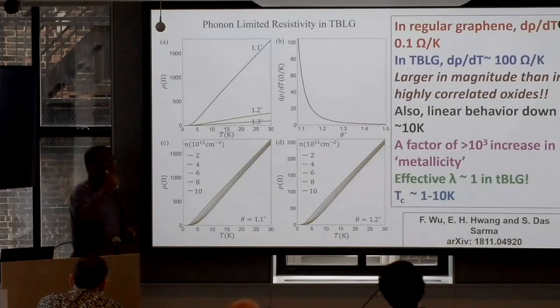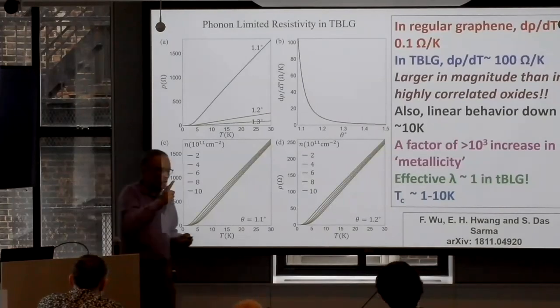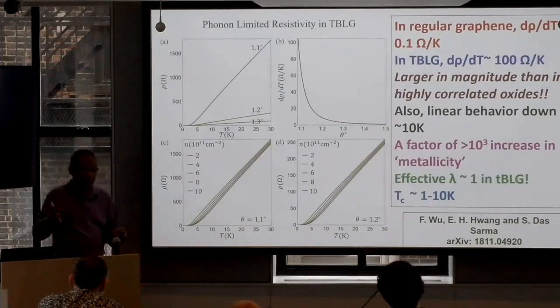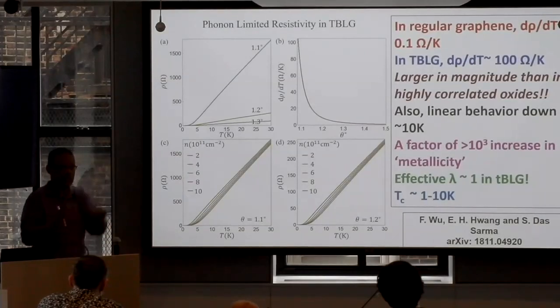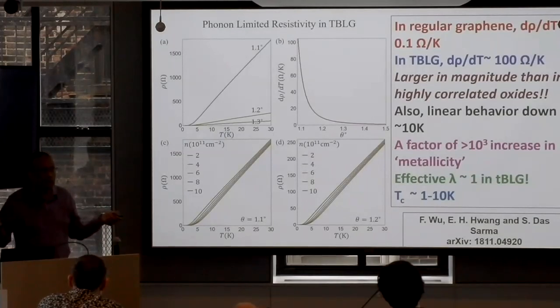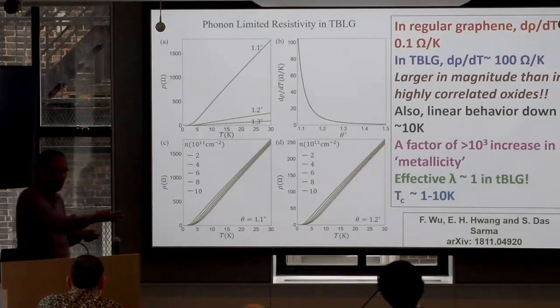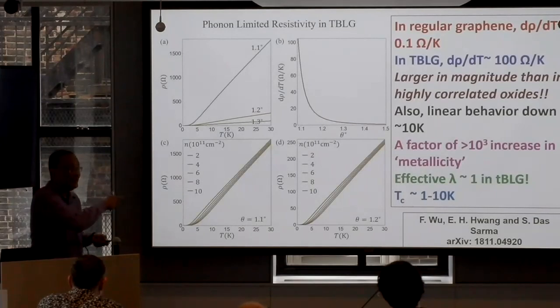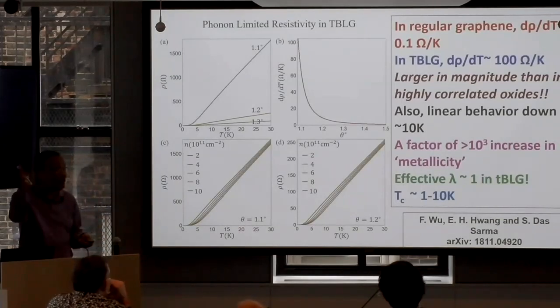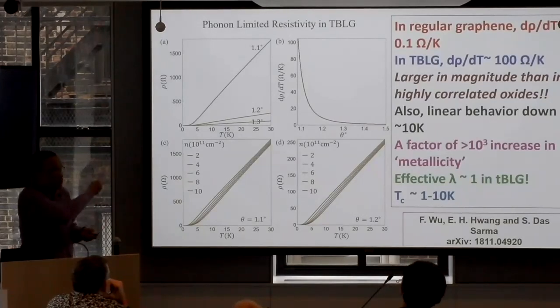You bring up a very good point. The basic deformation potential coupling most likely changes, and I'll come to that when I talk about superconductivity, okay? Because I don't know if you know, this deformation potential coupling, which basically means if you apply pressure, how much the bands change, it's not known very well even for a material like silicon or gallium arsenide, okay, experiments. So it's often set by comparing with transport experiments. And Andy, answering the question, we do need a larger value of D than what it is for monolayer graphene. And this is the open question. Some first principles person here perhaps can do this calculation. And referees bring up this question, and it's a justified question, but I'm talking about it, okay?